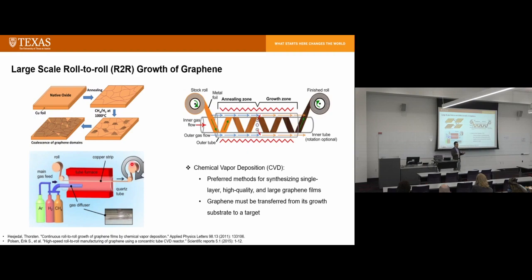So almost all the graphene research has been focusing on growing quality small-scale graphene, but there is research focusing on large-scale growth. They use a roll-to-roll process. They put in the furnace a roll of substrate material for single layer graphene. The most suitable material is copper, and you just unwind the copper roll going through the tube furnace, and then you wind it on for the finished product. Everything has to be in a controlled environment, so you send in your gases, the supply material stock, and you grow a single strip of graphene. You can grow longer depending on the facility you have.